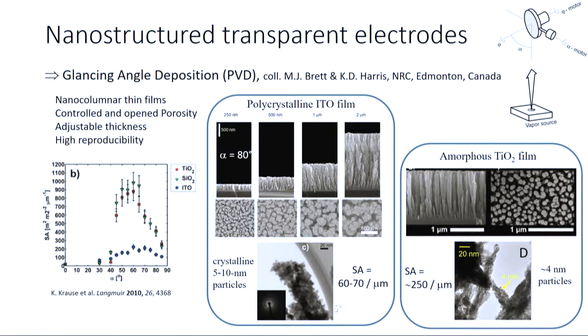And we mainly work with two kinds of nanostructured transparent electrodes: polycrystalline indium tin oxide film, where each nanocolumn is constituted by very small crystallites of indium tin oxide, and the surface enhancement is typically 60-70 per micrometer of film thickness. And we also work with amorphous titanium dioxide films, which are also constituted by very small particles of amorphous titanium dioxide, and the surface enhancement in that case is much larger.